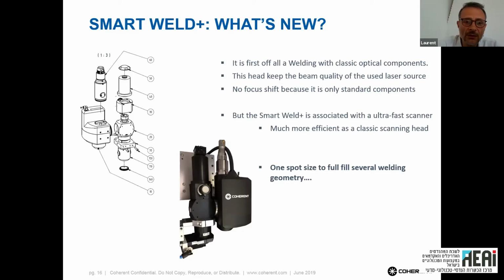And what is really, really important with a classic fixed welding head is the possibility to keep the beam quality. And if you are able to keep the beam quality from the laser to your part, this will definitely help you to weld in good condition. This will definitely increase the quality of the weld. So this head is really a mixture between a classic head and a scanner. This head is very compact. And the main advantage is the possibility to generate only one spot size. And with this spot size, to be able to fulfill more or less all the configurations I showed you, even the mismatch between the theory and the real parts.